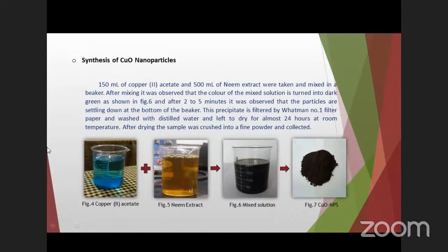Synthesis of copper oxide nanoparticles. To synthesize copper oxide nanoparticles, 500 ml of neem leaf extract and 150 ml of copper acetate solution is mixed in a beaker. After mixing, it is observed that the color of solution turned into dark green color. And after some time, 2 to 5 minutes, the precipitate settled down at the bottom of the beaker. After that, the solution is filtered by one number filter paper, and precipitate is washed by distilled water. After washing, the precipitate is left to dry for almost 24 hours at room temperature. After drying, the sample was crushed into fine powder and collected for characterization.